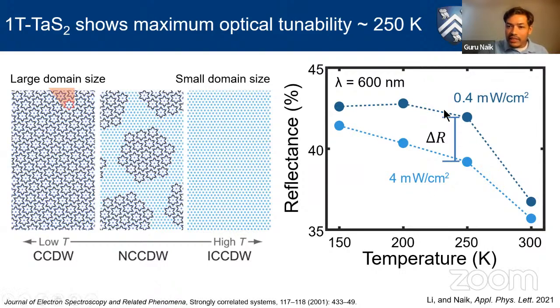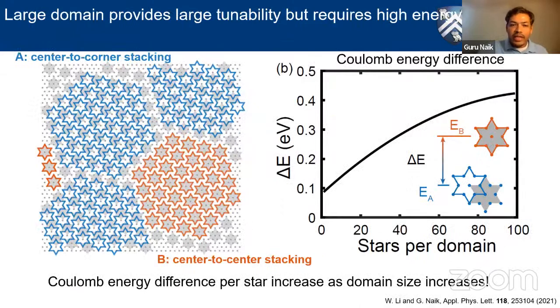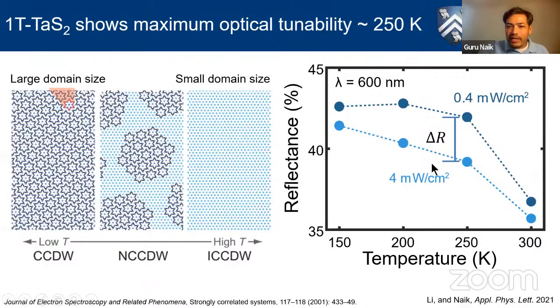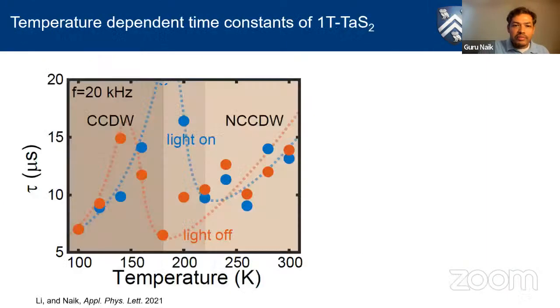The other thing that we saw was a maximum which was not anywhere close to any of the phase transition temperatures. We thought this is simply a competition between how many of them change, and how easy it is to change. As the domains grow bigger, the energy cost is high, so there is less probability of change. But when they change, because a bigger fraction of the sample changes, there is also a bigger optical response. So these two opposing factors give, somewhere in between, this peak in tunability or nonlinear effect. That's what we concluded from this particular work.